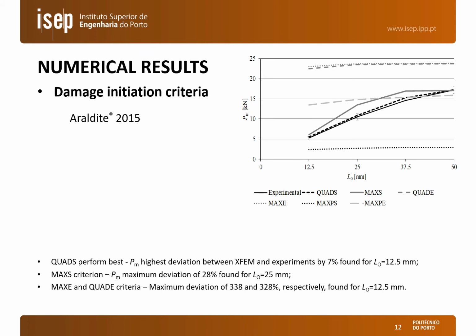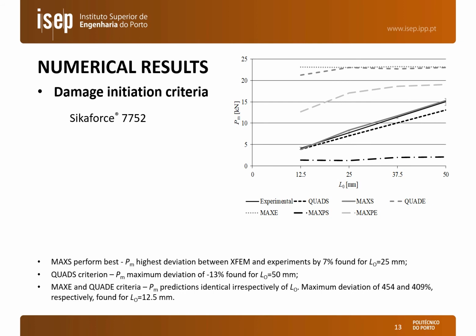For the max S criteria, the maximum error was 28%, and for the other criteria, the results were completely offset of the experimental behavior. Finally, for the Sikaforce 7752, once again, the max S and quad S criteria give the best results, and here for these two criteria we had deviations in terms of maximum value of 7% for the max S and 13% for the quad S criteria, and once again the other criteria, as you can see by the figure, are much offset from the experimental behavior.